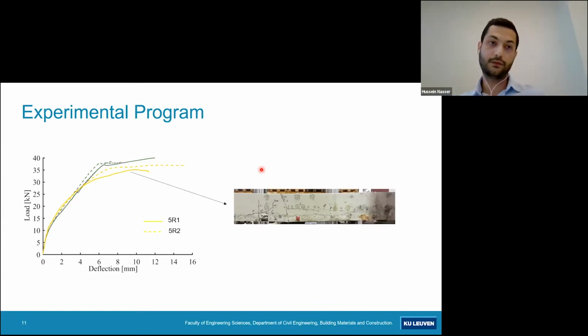If I move now to the corroded beams, I will discuss first those that have reached 5% mass loss of steel. It can clearly be seen that corrosion reduces the bending capacity and the stiffness of the beams. It's also noted that one of the beams, the curve which doesn't show a distinct yield point, has developed a splitting crack, which indicates bond failure due to bond deterioration. So not only does corrosion reduce the yield capacity,